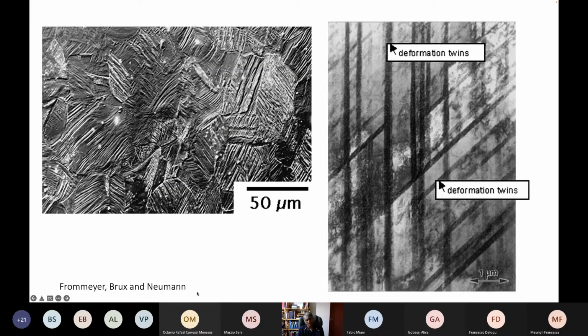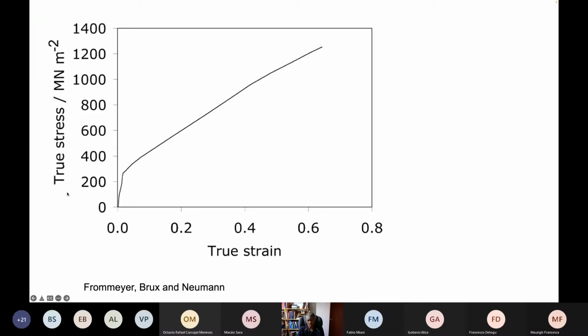Okay, TWIP steels. So this is a very classic paper. The reference to this will appear later in the presentation, showing austenite which deforms by mechanical twinning and dislocation slip. So this was a sample which was originally flat, and after deformation you can see all the surface relief here caused by mechanical twinning in the different austenite grains. And in a transmission electron micrograph, these twins are extremely thin, okay, because of the very large shear deformation. And of course, you also have an increase in dislocation density, because it's not just twinning alone, but also dislocation slip that occurs at the sort of deformations we subject twinning-induced plasticity steels to. I'll tell you the composition later, but these are quite remarkable materials, because look, this is a stress-strain curve.